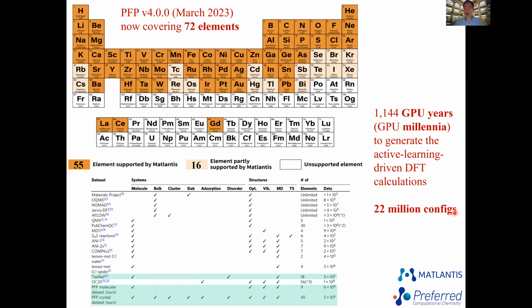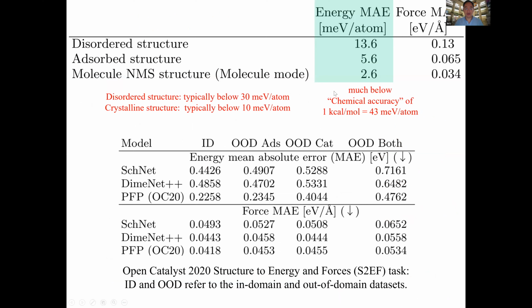So the active learning-driven sampling has now generated more than 22 million configurations, which is already much bigger than when the Nature Communications paper was published. And we have compared with the catalysis data sets with SchNet, DimeNet, etc. And generally for disordered structures it is a bit higher in error. But generally the point is that we're able to fit DFT quite better than what we know that DFT can represent reality. So we're kind of reasonably satisfied with the framework itself.